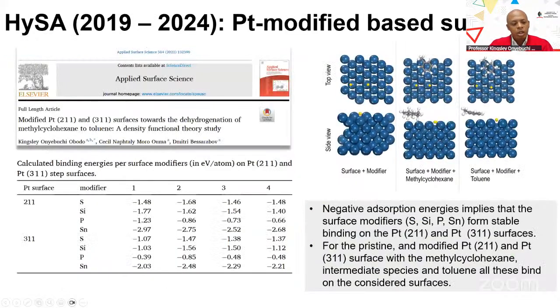So what we've done generally here is to ask ourselves, how can we improve this catalyst? How can we improve platinum? So what we've added is surface modifiers, where I added different elements: silicon, sulfur, phosphorus, and tin. These elements were not just selected at random, they were selected because they can poison the surface catalyst. So we asked ourselves, at what percentage of loading is this catalyst good?